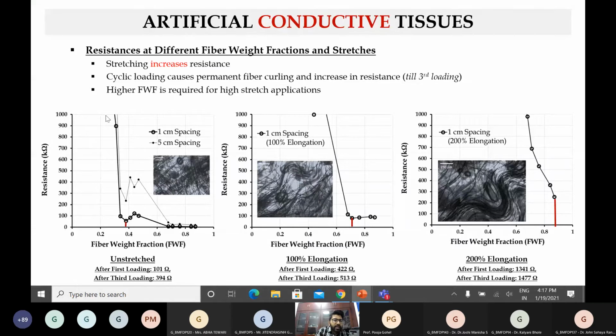So we tried to run a bunch of tests and look at what the resistance is at a common spacing of, let's say, 1 centimeter. If we took 1 centimeter on this specimen, or at any point, and a 5 centimeter spacing, what kind of resistances are we looking at? The dark line here is the 1 centimeter, and the 5 centimeter is the much thinner line. So we are looking at resistance versus the fiber weight fraction.